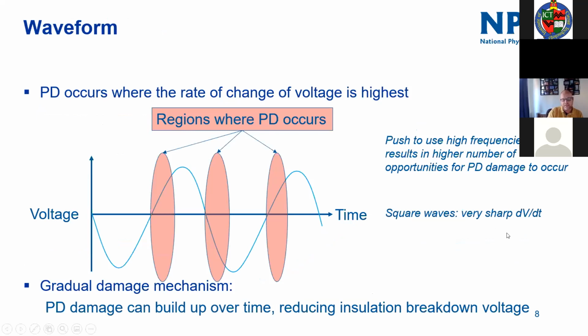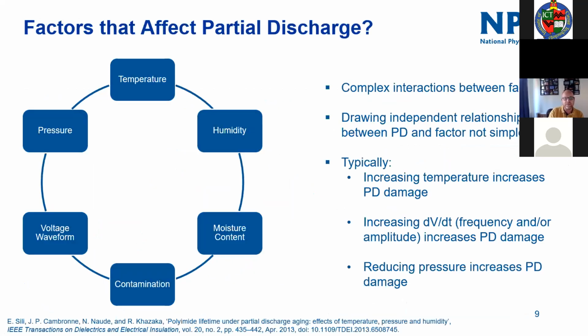PD is related to a change in voltage with respect to time. So it's related to dV/dt. And so it's predominantly a phenomena associated with AC signals or switching power signals. And it generally occurs in the region where the change in voltage is greatest with respect to time. So that's in the up curve of a sinusoidal AC system. Obviously in a square wave, it's at the very start of the square wave, depending on how long it takes you to build to your voltage. And it can occur repetitively, it can occur on the plus and the minus side of the cycle. And it's well known within the power electronics or the power distribution industry that this PD can build, it can cause damage over time, and eventually ends up in breaking down the insulation resistance of the system. And again, hopefully I'll show you some brief examples of that later.